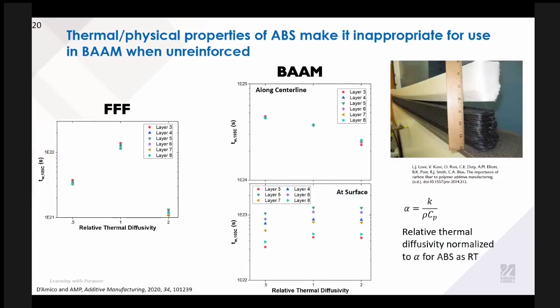One of the things that motivated our work in extending our model from the FFF scale to the BAAM scale was to try to answer a question that was important in the BAAM world. So when BAAM was first set up, there were attempts at printing with just pure ABS, and the ABS warped by a large amount. You can see in here, a bar of the BAAM printed ABS is warping by about an inch, and so that's not really tenable for large structures to have that much warping. They were trying other materials and found that chopped carbon fiber filled ABS, which is shown here in black, doesn't warp at all.